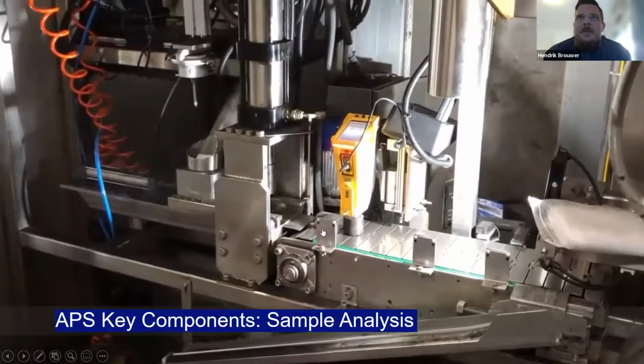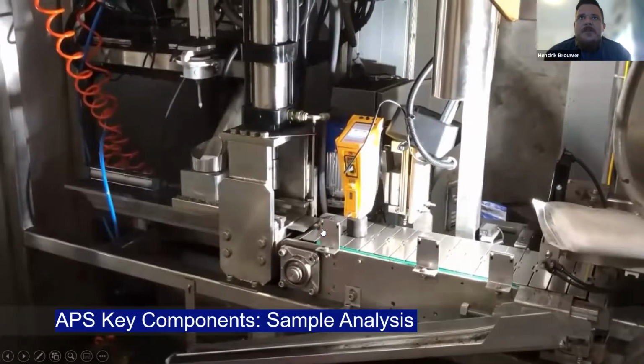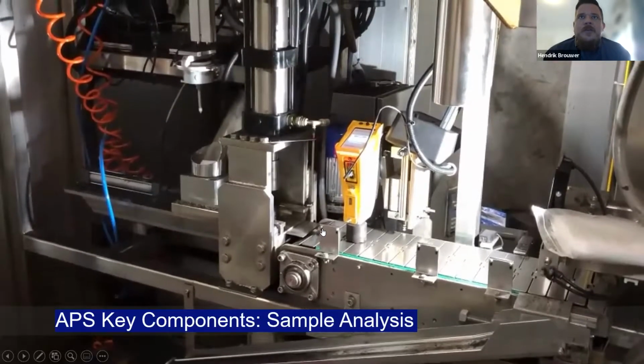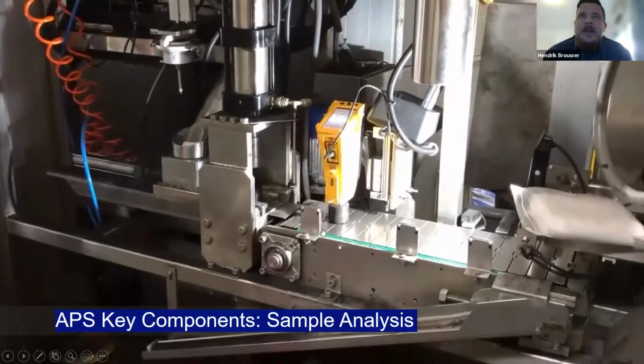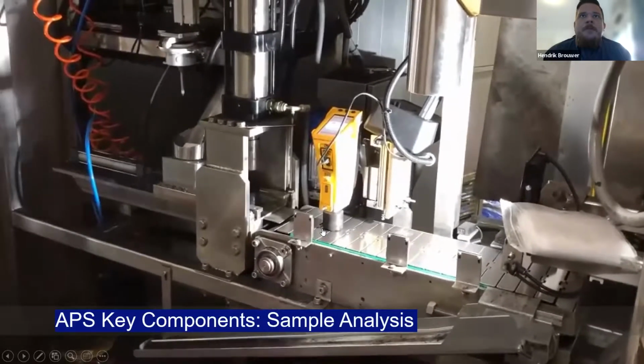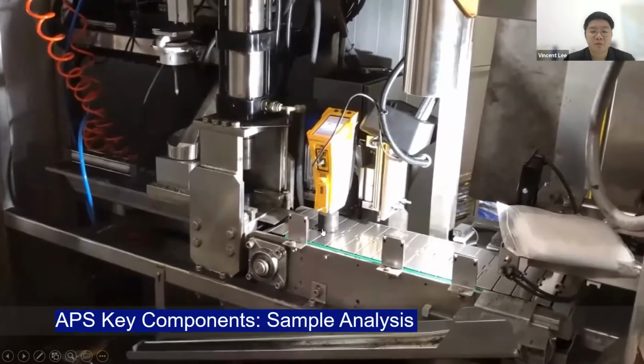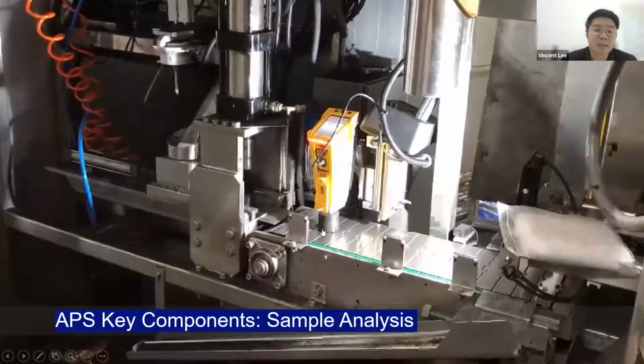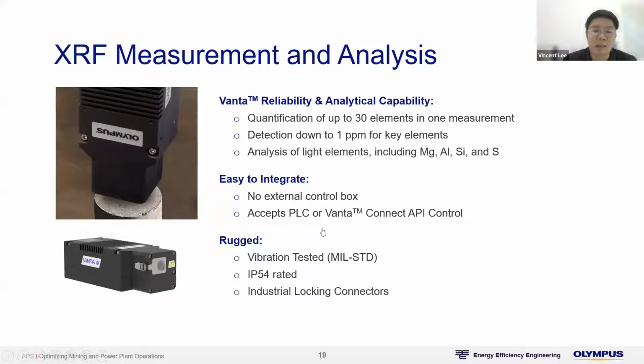It comes down to the same features as what you know in your handheld XRF are actually in the Vanta iX. Isn't that correct, Vincent? Yeah, that's right. With the Vanta IX, in terms of reliability and analytical capabilities, it is exactly the same as the handheld XRF. It can measure up to 30 elements in one measurement, and for certain key elements, we are able to measure down to 1 ppm if required.